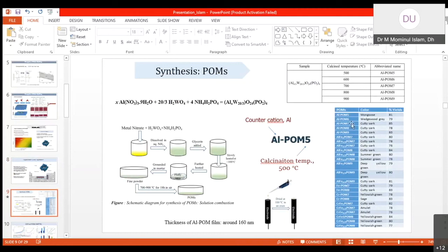We have synthesized all of the polyoxometalates given in these tables using the solution combustion method, which is a very conventional method. In this case, very simply, we add some glycine fuel to the system, and the precursor is heated in a tube furnace in different environments, especially oxygen and nitrogen. We get this catalyst, and here is the definition of the catalysts synthesized in our work. Aluminum means the counter cation, POM is polyoxometalate, and the number defines the temperature at which the polyoxometalate is calcined. In some cases we can see two types of counter cations, which means mixing two counter cations to get the benefit.